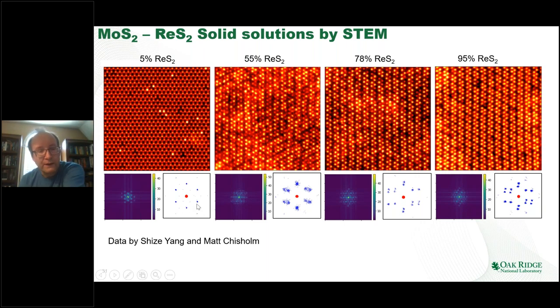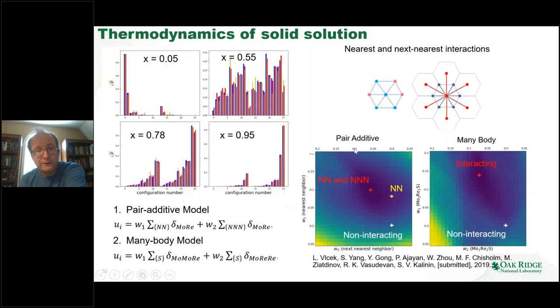At pure phase, you have a sharp single peak, then peaks start to split and broaden. So broadening is the disorder, splitting is the phase transition. And then if you keep doing it, the peaks become narrow again, but they have already split. So you're out of the phase transition region into the new phase. The question becomes: if our theory worked for an idealized model, will it work for experimental data? The answer is yes, it will.